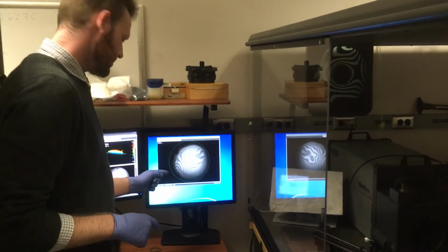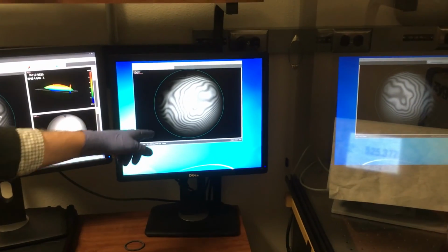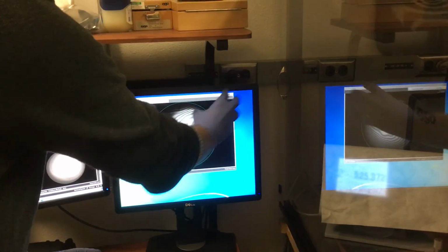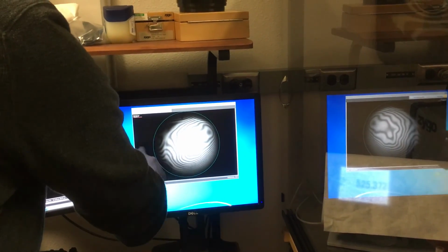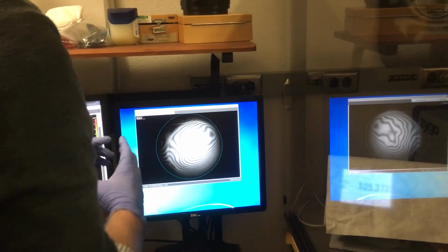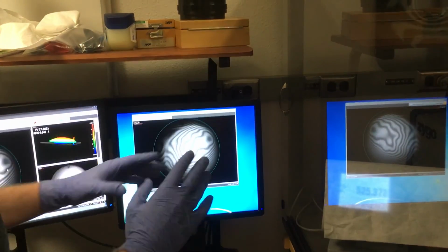So this was our first deposition from sputtering, and you can see we missed the center of the wafer by quite a bit. We were off center a little bit this way, so you can see there's a lack of film here, which makes the fringes shifted up and have a weird shape.